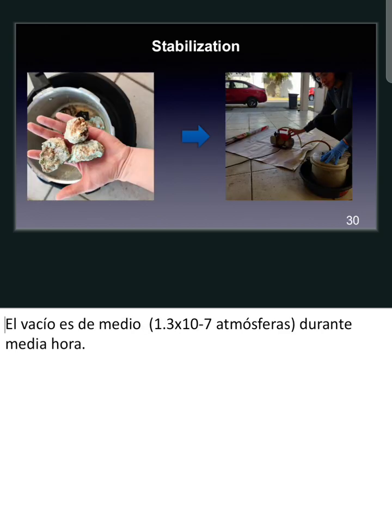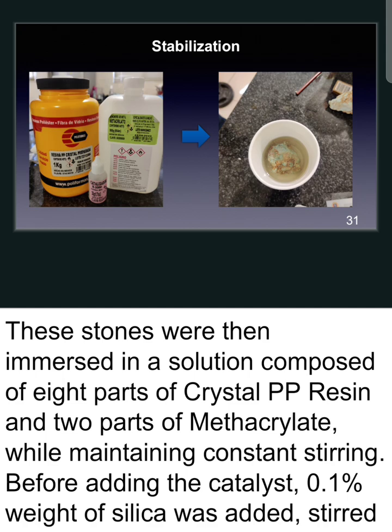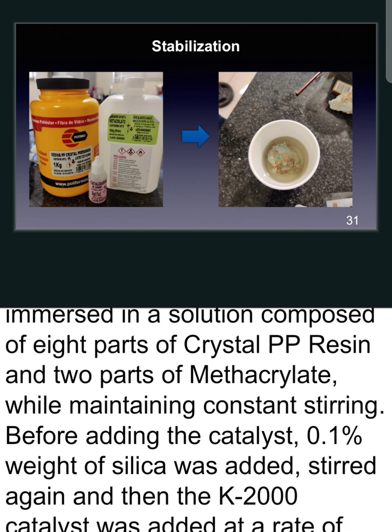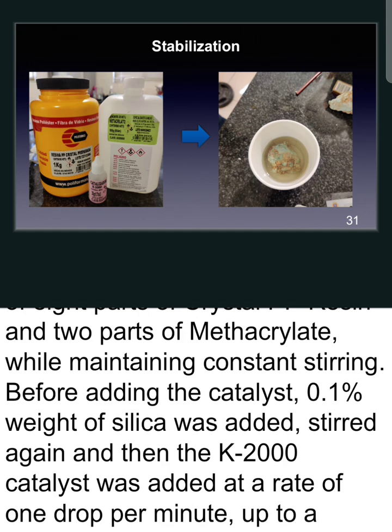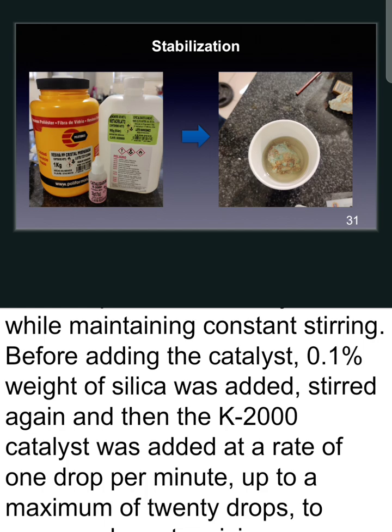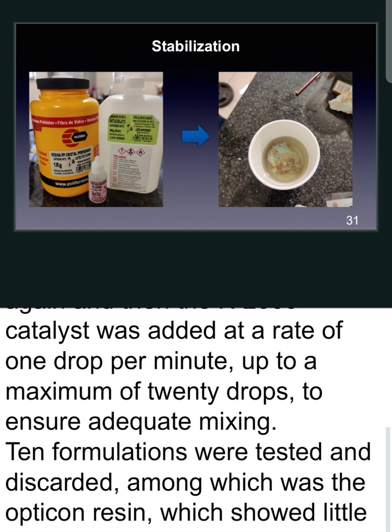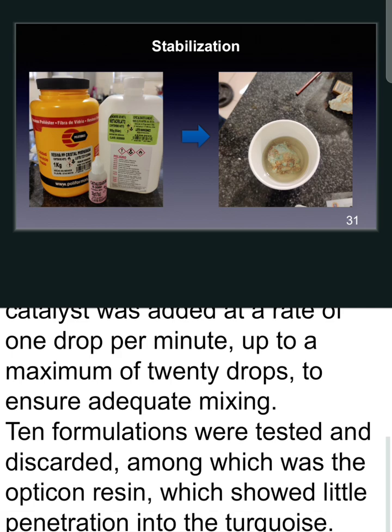Talking about the stabilization, first we select our chalk-grade gemstones, and then we put them at medium vacuum during half an hour. Then these stones were immersed in a solution composed of 8 parts of crystal PP resin and 2 parts of methacrylates, while maintaining constant stirring. Before adding the catalyst, 0.1% weight of silica was added, stirred again, and then the K2000 catalyst was added at a rate of 1 drop per minute, up to a maximum of 20 drops to ensure adequate mixing. 10 formulations were tested and discarded, among which was the opticon resin, which shows little penetration into the turquoise.